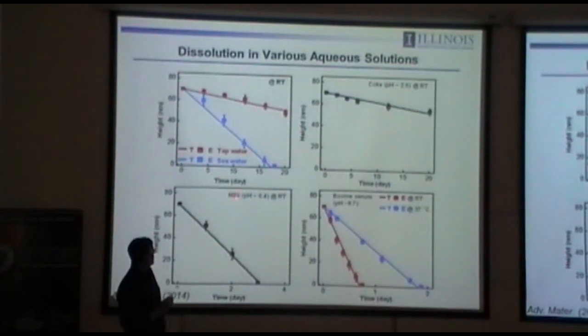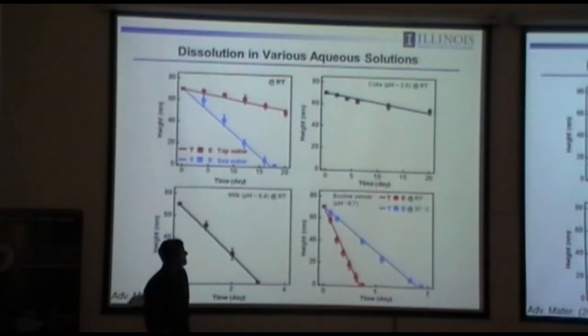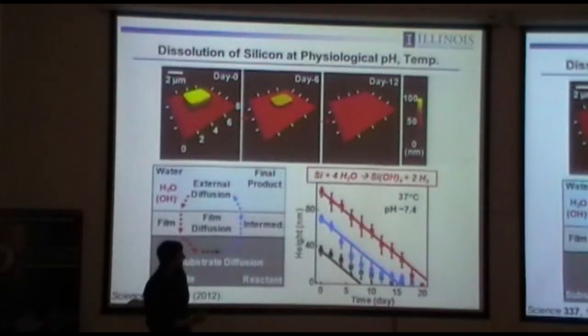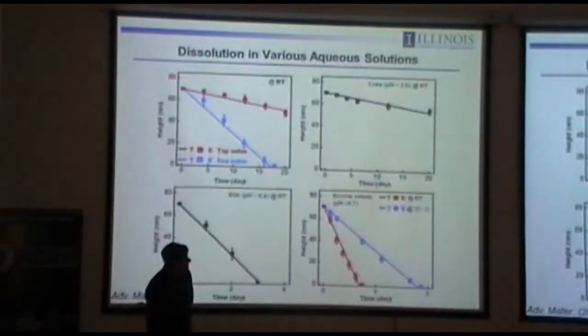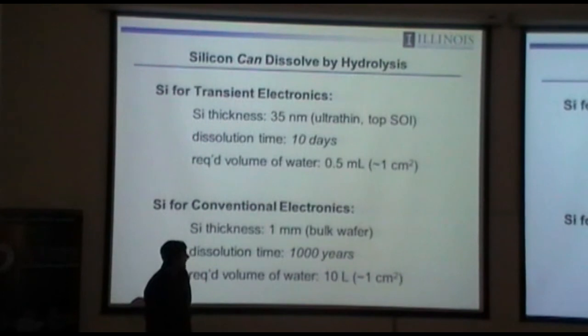Tap water, seawater, milk, bovine serum. We even put it in Coca-Cola. It slowly dissolves. Interestingly, it's slowest in Coke. You would think that would be the most corrosive thing possible. But the problem is the pH is low, and you need hydroxyl ions in order to drive that chemistry. So Coke is pretty corrosive, but not so much for silicon. So anyway, you can do that.